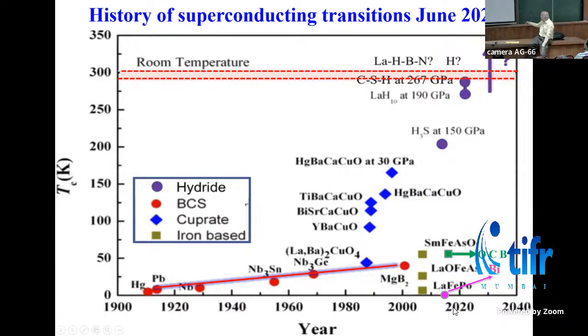And well, we were the guilty ones who brought this superconductivity down close to 0 with bismuth. And the other one, which is equally interesting, is what they call Q carbon. It's an amorphous form of carbon which will melt, suddenly cool, and it goes to a special allotropic version of carbon. The important point is that this carbon absorbs a lot of boron, and that gives rise to this fairly high TC superconductivity. 55K is no joke.